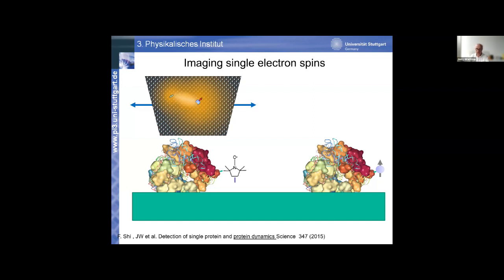The protein in itself is diamagnetic, so it contains no electron spins. The only source of magnetic field would be the nuclear spins, like protons or carbons, but these we were not measuring in this experiment. So if you want to make this detectable by your sensor, you would need to put in an electron spin. And this is what people do in biochemistry rather routinely. You can take a small molecule here. This is a nitroxide radical. Nitroxide comes from the nitrogen, which is otherwise in a carbon environment. And this has a dangling bond. And in this dangling bond, an unpaired or unbonded molecular orbital, there is a single electron residing.